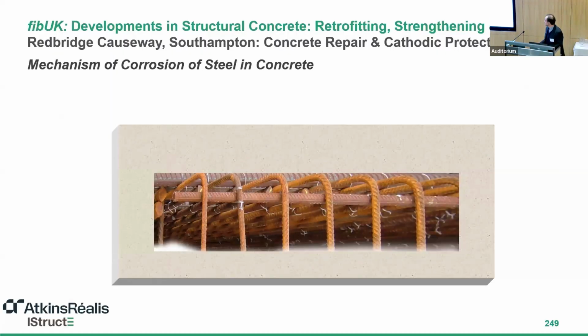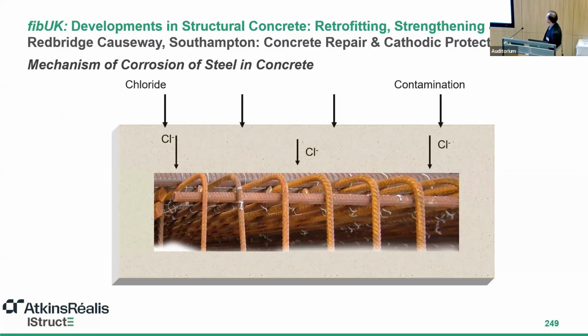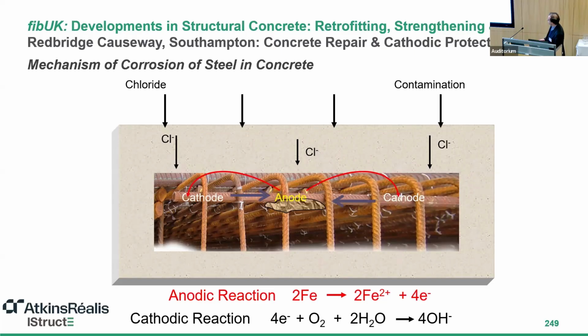As you may know, the steel reinforcement in concrete is generally protected by the alkalinity in concrete, and because of the formation of the very dense oxide layer. So once environmental elements like chloride and carbonation start to diffuse into concrete, then the anodic and cathodic sides start to form. In the anodic side, effectively iron gets dissolved into the pore solution and releases an electron, and those electrons have to be consumed somewhere, which is the cathodic side.